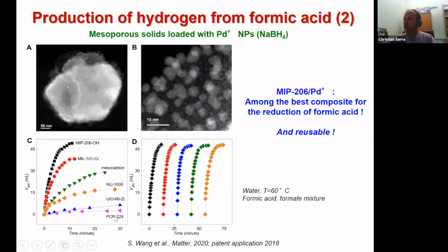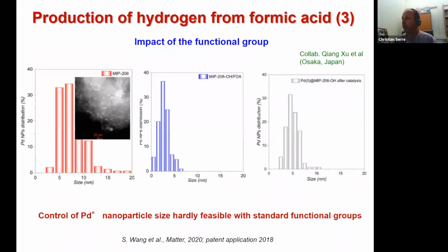They compared it with benchmark MOFs like PCN-224, NU-1000, or MIL-101 chromium, and then a commercial mesoporous carbon. They could see that under the conditions tested, our material with the OH functional group behaved the best. And not only that, but they could recycle it 5 times. So it was shown that this MOF was totally reusable despite the harsh conditions.